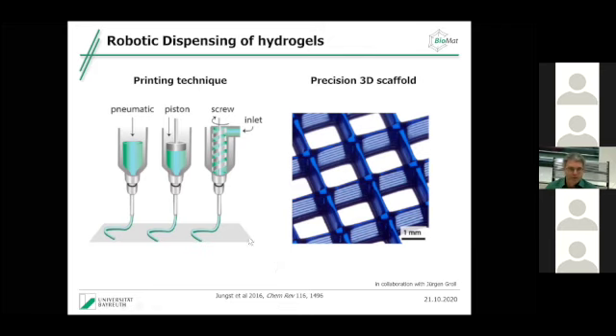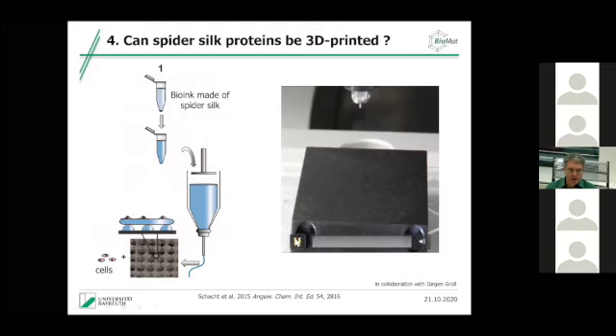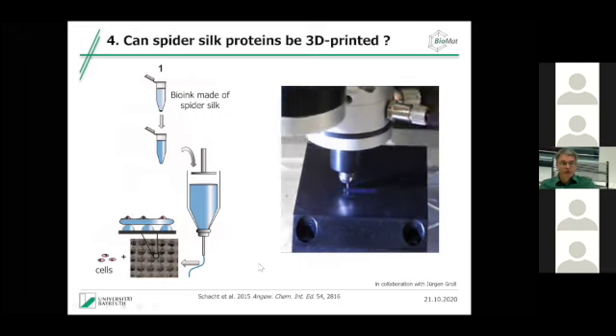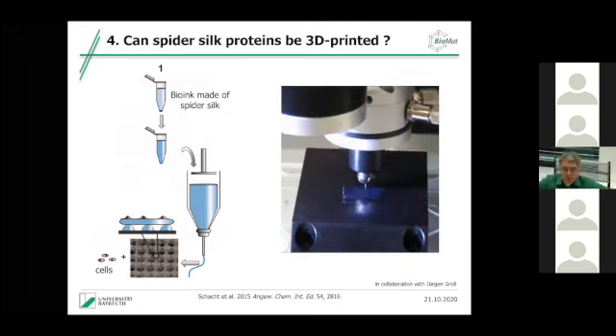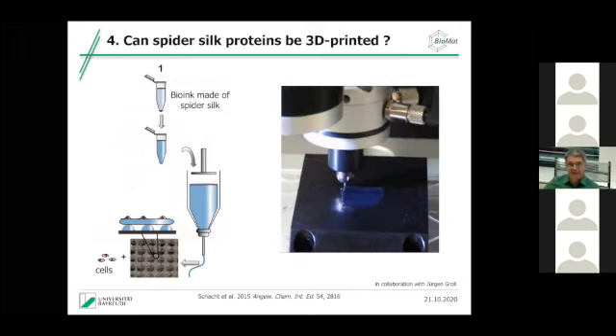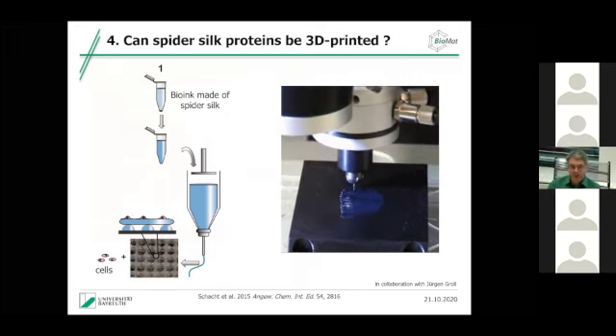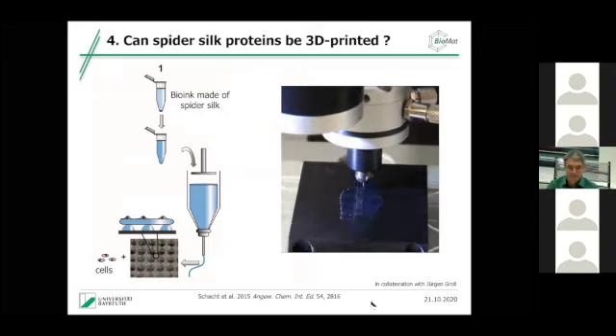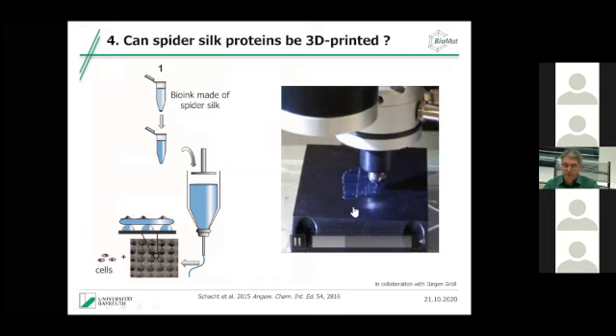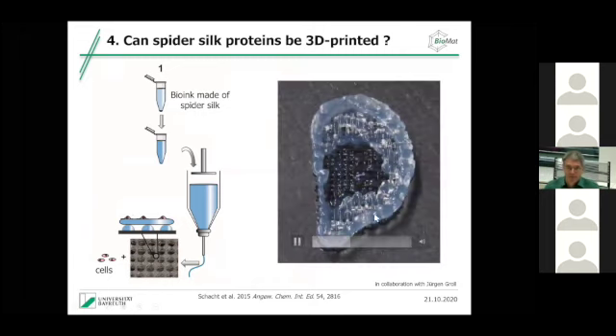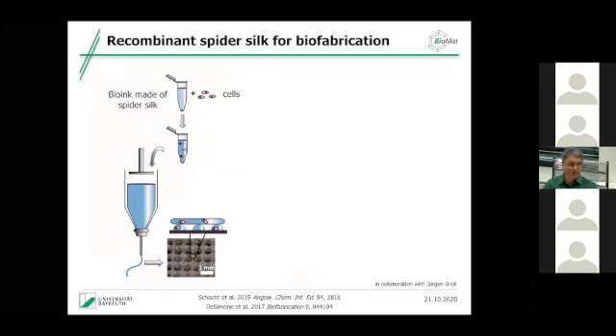Okay, so can we do that with spider silk? This was the first test, and you see here a 3D printing in real time. You see it immediately hardens as soon as it leaves the needle, and you immediately can start with the next layer. And the first idea was, well, now we 3D print the stuff, and here we 3D printed something that looks like an ear, 64 layers, and then we actually inoculated cells on top. The drawback of that system is, and this is for all kinds of tissue engineering approaches, that the cells have to go into the scaffold and find the places.